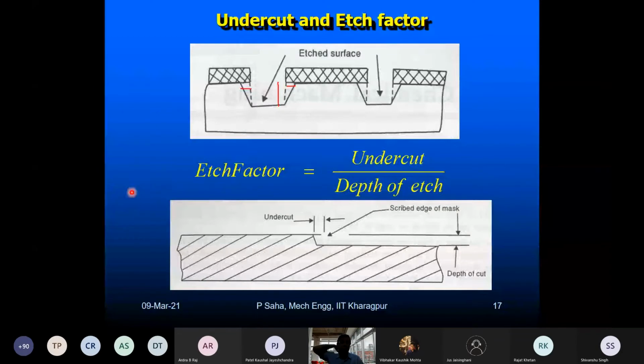Now coming to the concept of undercut and etch factor. Now when you achieve a certain depth, say this red color, this is my depth of machining, and I want to machine up to a certain depth. So this is the depth of cut. Okay, but you see, because of the side machining, as you penetrate with time, there will be some amount of machining on the sides, and on the top portions there will be more machining, and down to the bottom the side machining will be less, because the bottom portion is exposed for less amount of time to the chemical. Okay, so we get a tapered surface.